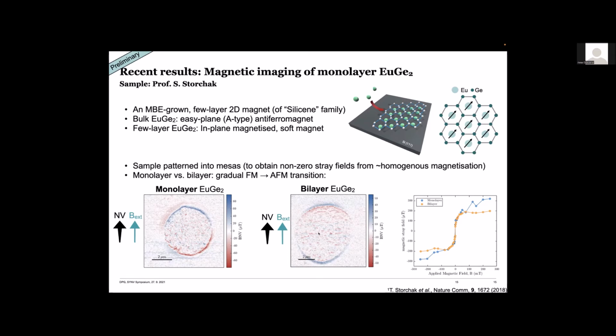As I said, this is preliminary data. We're trying to understand how this magnetization evolves with layer number. And one thing I can also say here is that the stray magnetic field, if we analyze this quantitatively, is not compatible with a homogeneous layer of magnetization. There must be some canting happening in this material, which again, we're trying to understand. And here, by the way, just to quantify this more, this is a magnetic field dependence of this magnetization strength. And you see once more that actually the bilayer saturates at a lower net magnetization as compared to the monolayer.